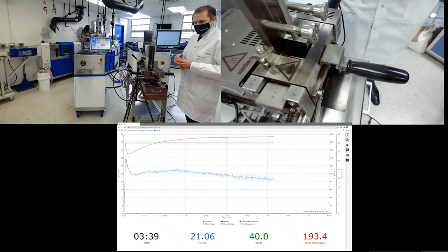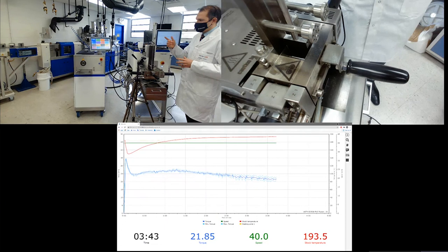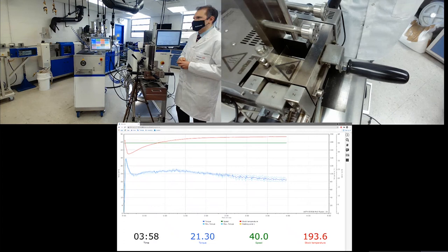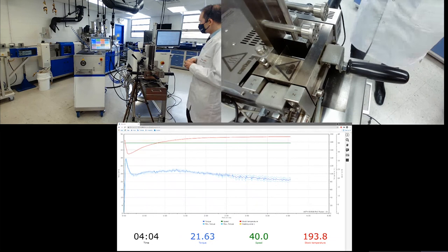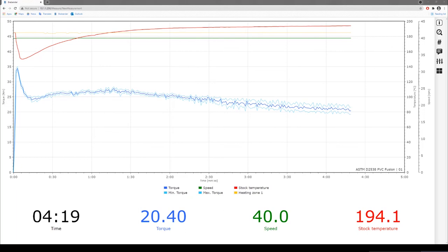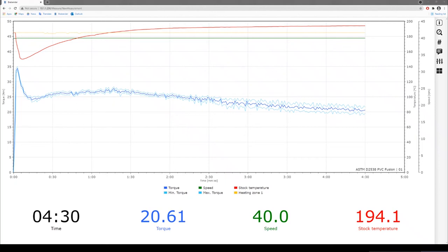In the bigger version, 400 newton meters. This is the concept that has been Brabender's signature drive since the beginning conception 97-98 years ago. Let's go back to the curve, so we're almost approaching the end of the test. You see we also have always an upper and the lower margin where we do the average. We take six measuring points per second and make an average of one, but it shows you the bandwidth of that. As the material continues to lose a little bit of molecular weight in its stability phase, you see that the bandwidth also increases at the very end.